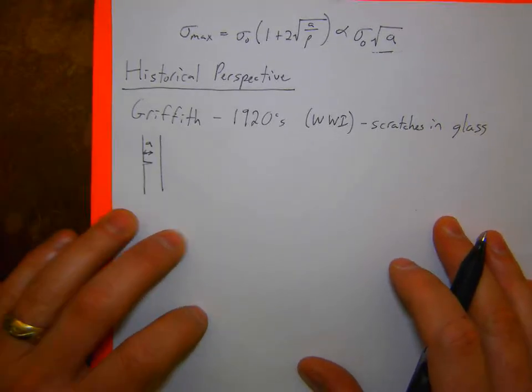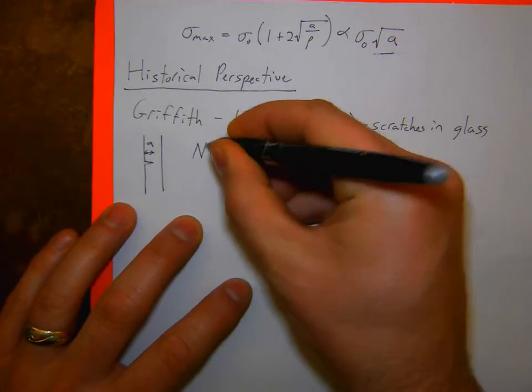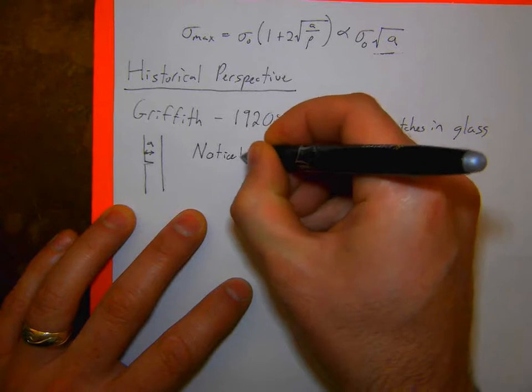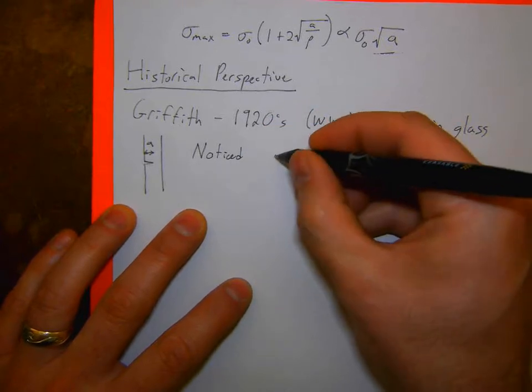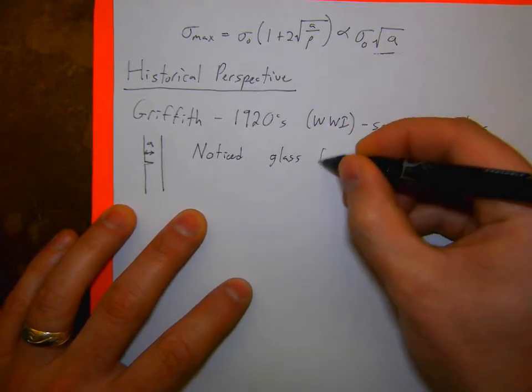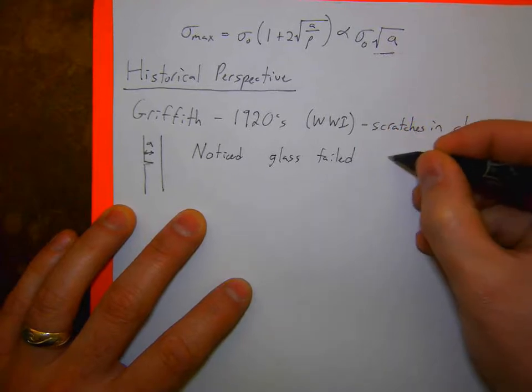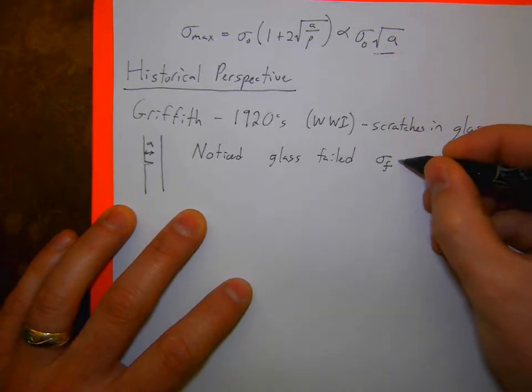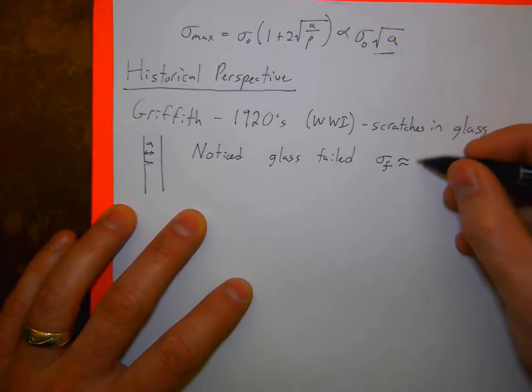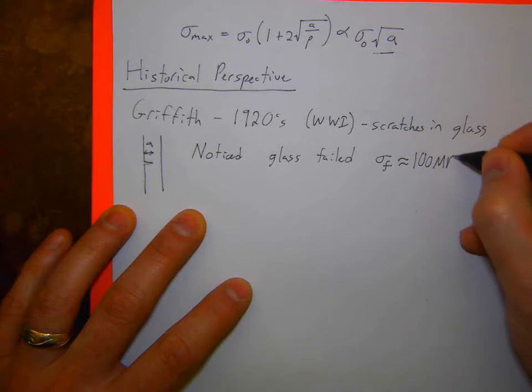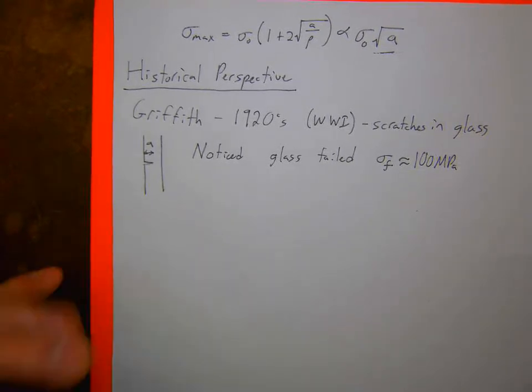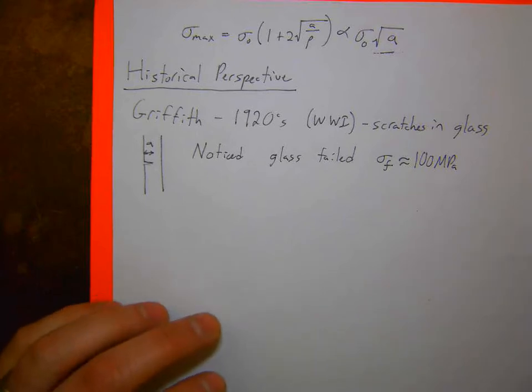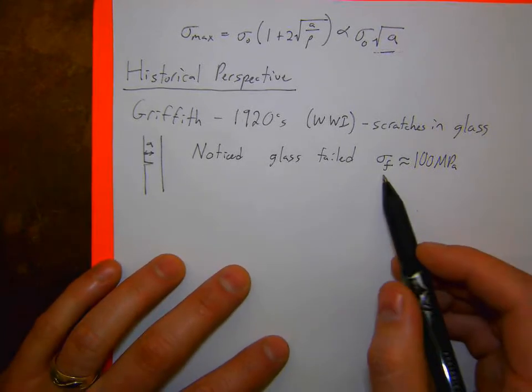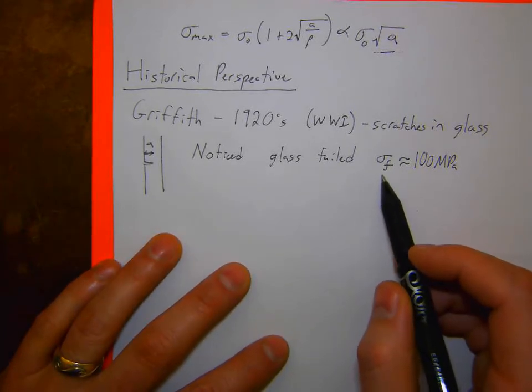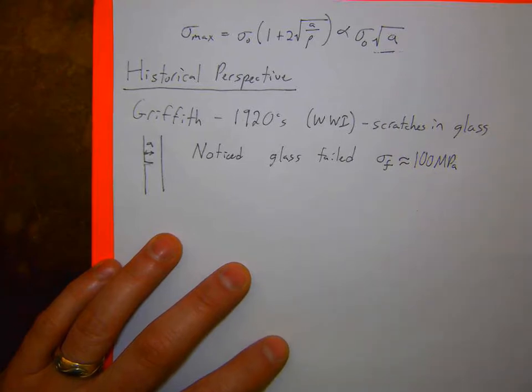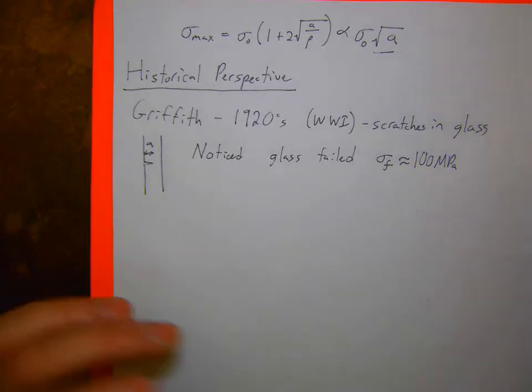And he started noticing, he noticed first that glass failed around a fracture strength of like 100 MPa, 100 megapascals, which is reasonably high, but it wasn't great. And so he started realizing that this was important, because sometime prior to that, there had